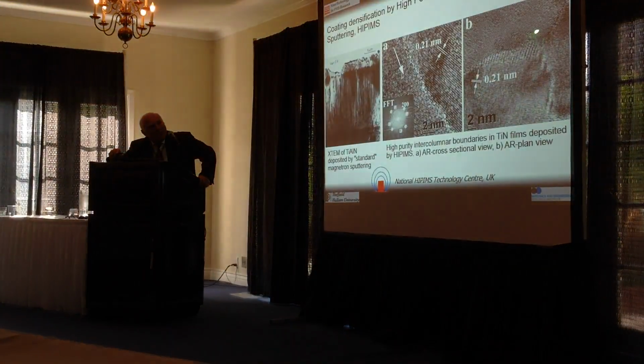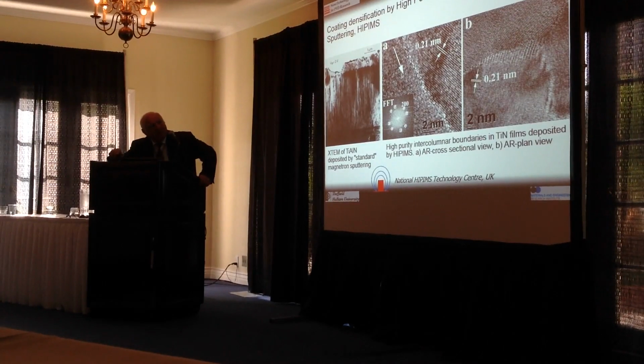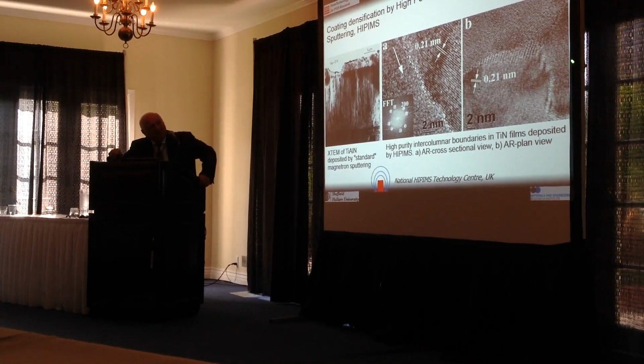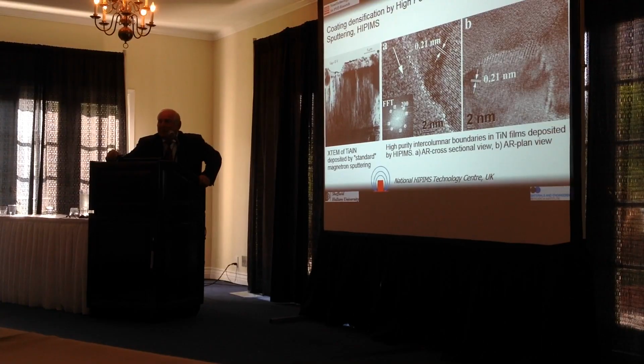These are the columns, and these are the column boundaries. So this is a 3-point meeting point between 3 columns, and you can see clearly the atomic plane from this column continuing in the next column, and there is no mismatch, no voids or imperfections. So this is a really bulk material type of testing.